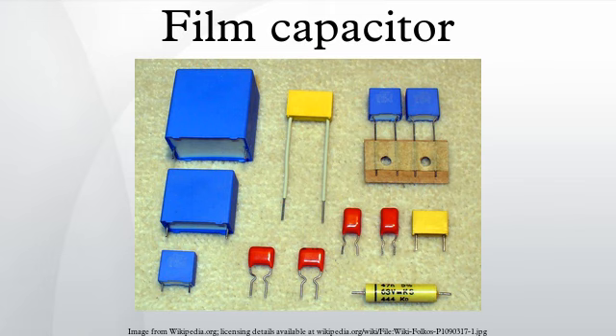Aging. Film capacitors are subject to certain very small but measurable aging processes. The primary degradation process is a small amount of plastic film shrinkage, which occurs mainly during the soldering process, but also during operation at high ambient temperatures or at high current load. Additionally, some moisture absorption in the windings of the capacitor may take place under operating conditions in humid climates.